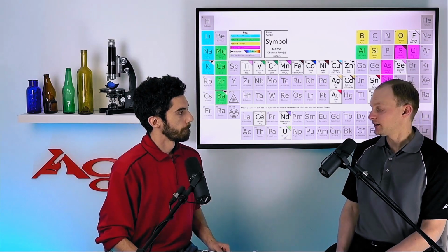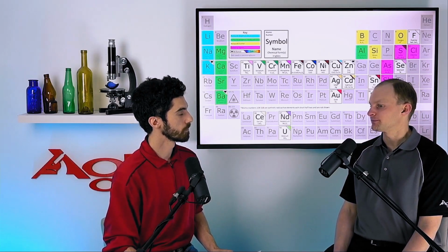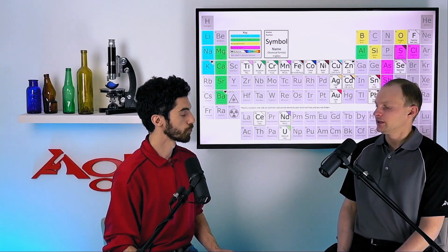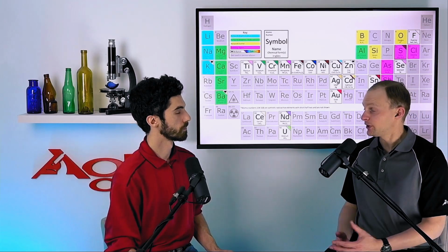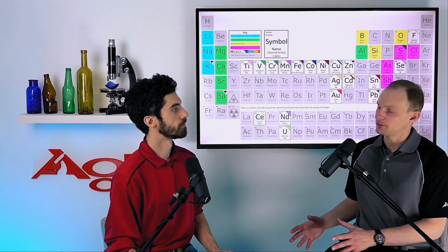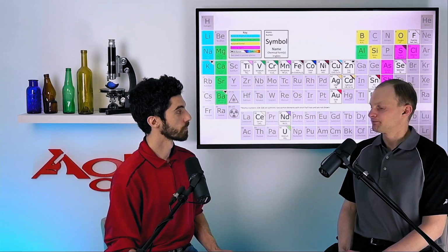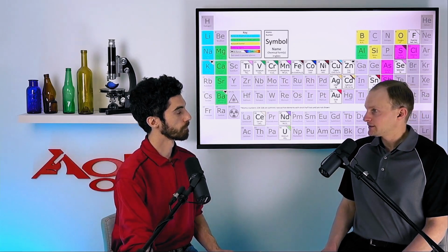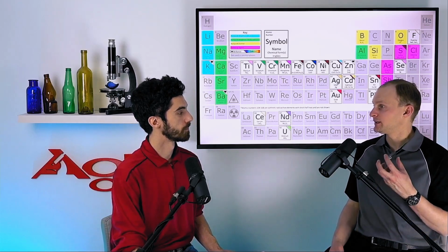Well, typically, the colorant won't affect the strength. I think they might be referring to things like alumina, which do have an effect on some of these properties. But typically, at least on the standard soda lime silica composition, we may not see too much effect on mechanical properties, like hardness. If we really start getting into a full aluminosilicate glass like is used for your cell phone screen, now we're talking a much different composition, and you are affecting things such as fracture and hardness and other properties mechanically. Certainly the brilliance, and I think what else did they mention? Brilliance, radiance, and color distortion. Okay, I'm not sure what they mean by radiance, but certainly color is important, and the brilliance is another factor.